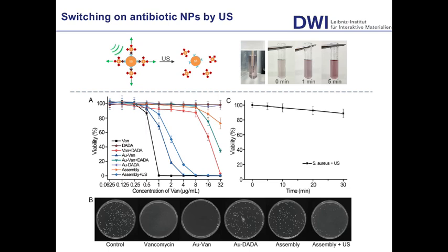You also see bacterial growth curves that show that the nanoparticle networks can be activated once you apply ultrasound to the system. You also see that the ultrasound itself doesn't kill Staphylococcus aureus, so Staph aureus is quite resistant to the ultrasound conditions that we apply here.